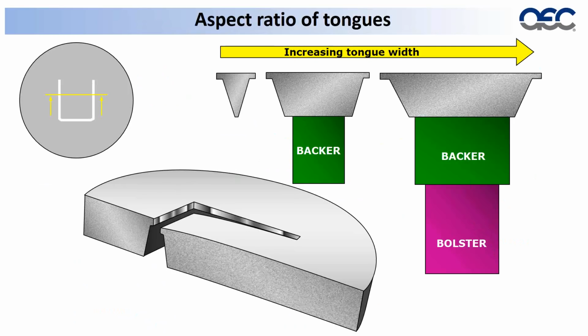So what you're getting here is, if you ask for a very narrow, very long tongue, we can't put support into the die backer and we can't put it into the bolster. So that thin die plate on its own has to resist deflection on its own. So one of the most challenging things you can make in extrusion is a long, narrow tongue. So one of the things we're going to discuss here is how we can design that out of the die by changing shapes a little to get you what you need as an end customer, but to make it extrudable for us.